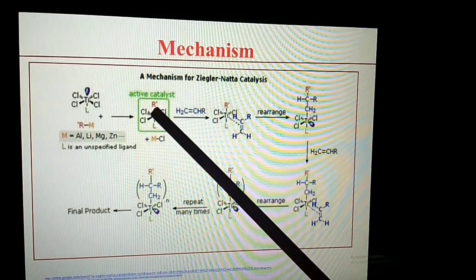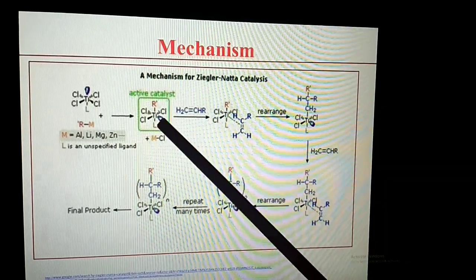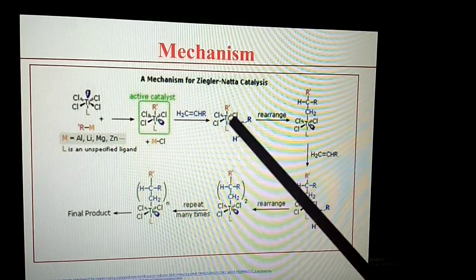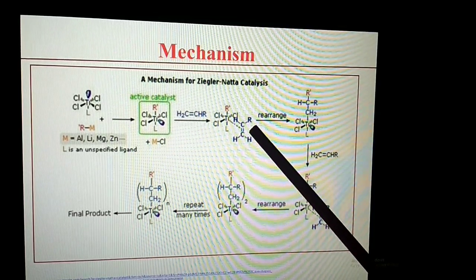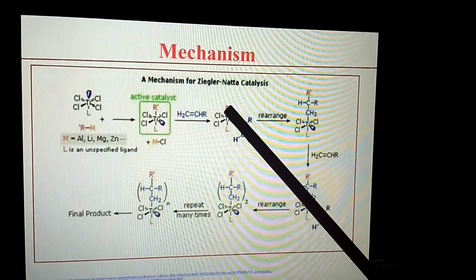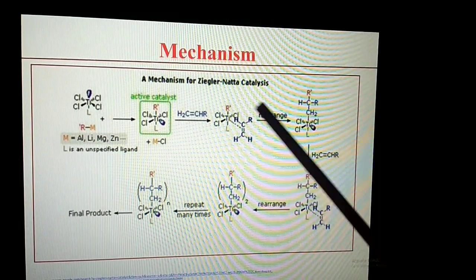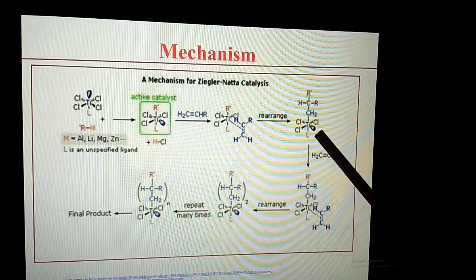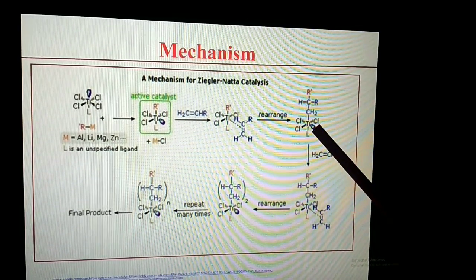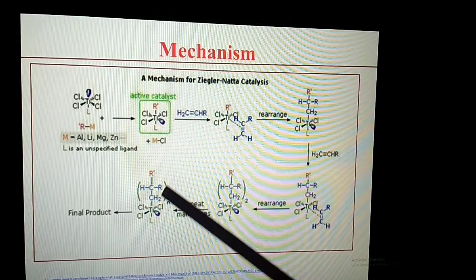In the next step, with the addition of an olefin, interaction takes place between the transition metal and the pi electrons of the olefin. Then migratory insertion takes place into the Ti-C bond, that is the Ti-R bond. The monomer molecule (R-CH=CH2) is inserted into the Ti-R bond. This generates a new vacant coordination site for the next attacking monomer, which then migrates into the Ti-R bond to form a long chain polymer.